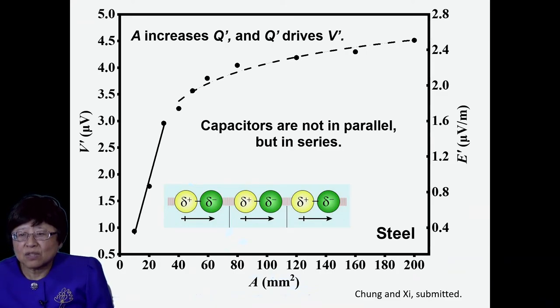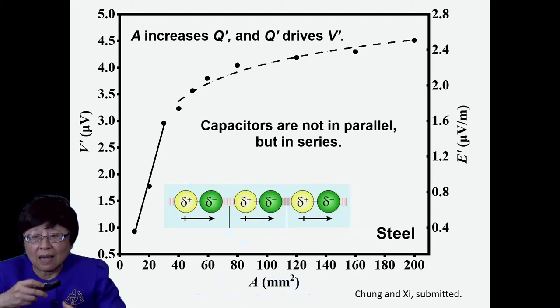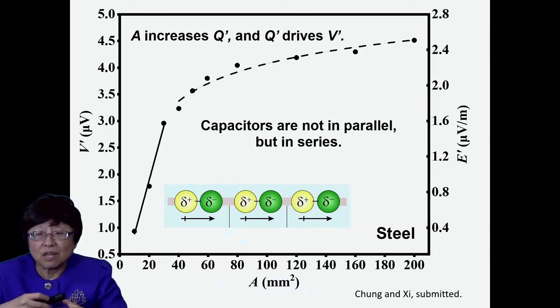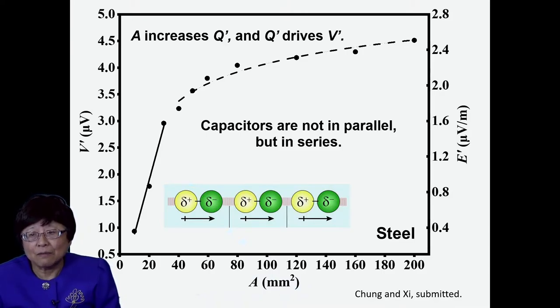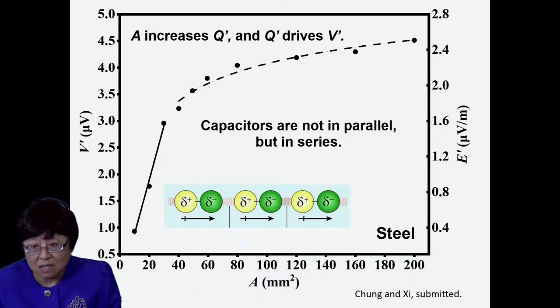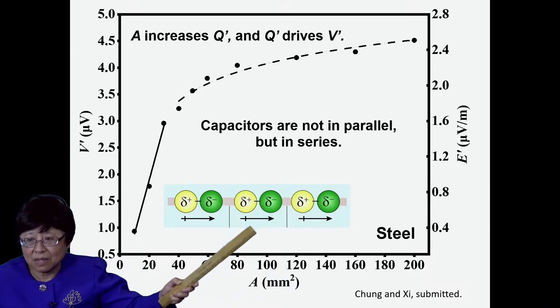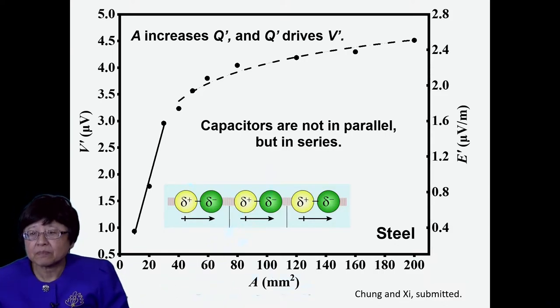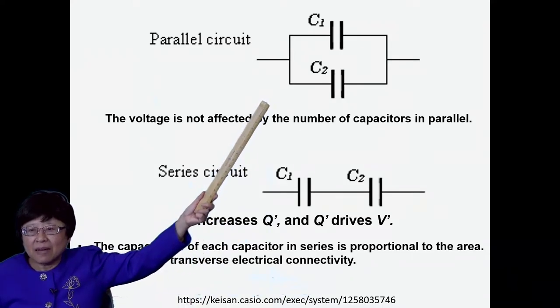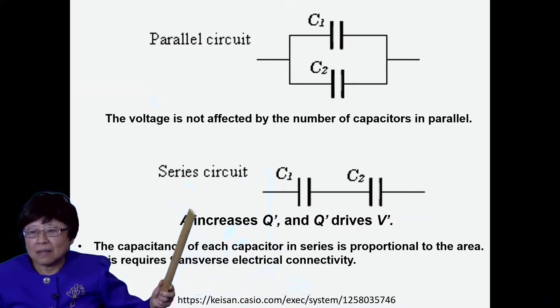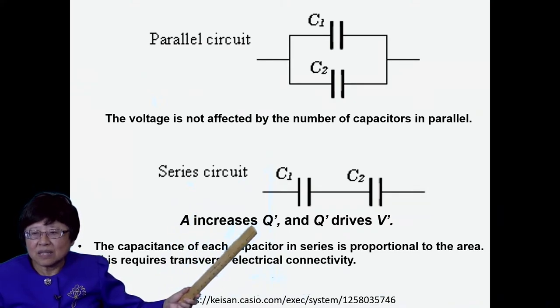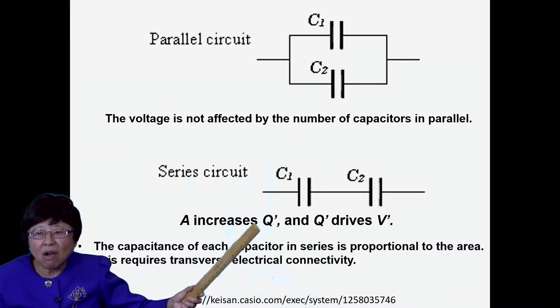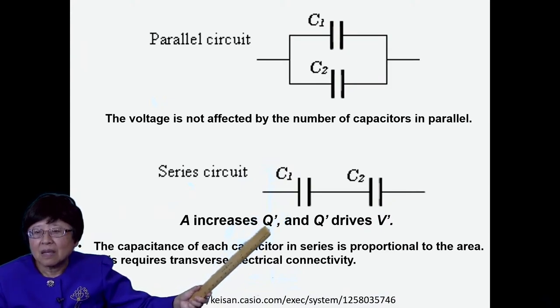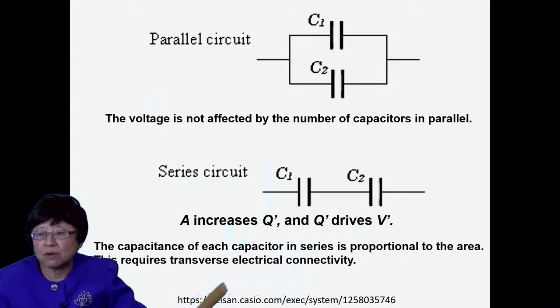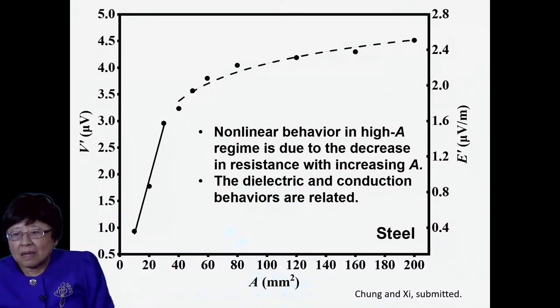This means that the capacitors are not in parallel, but in series. Because if, when you increase the width, that increase in width is associated with more capacitors in parallel, then the voltage should not change. But the voltage indeed increases with area. That means it's not in parallel, but in series. This is low-carbon steel. This is capacitors in parallel, capacitors in series. So in series, you have the area A increasing, increasing the charge, which we call Q prime, in the capacitor, and then the Q prime drives the voltage V prime.